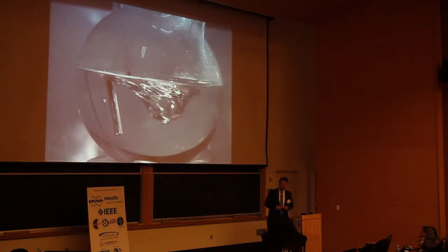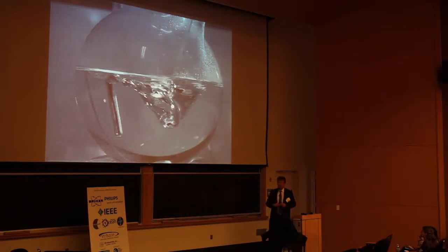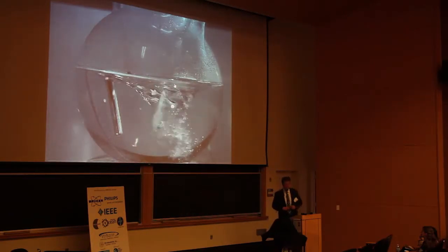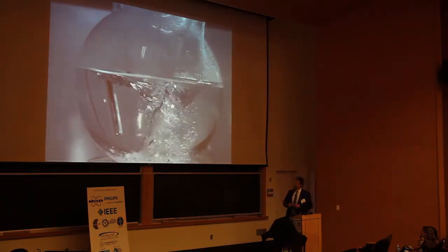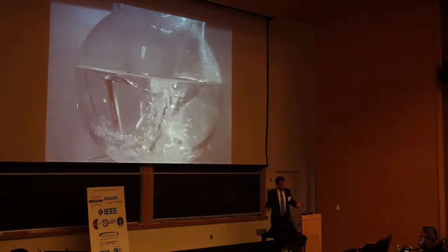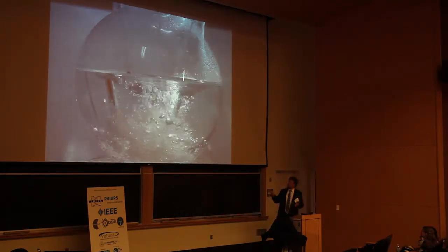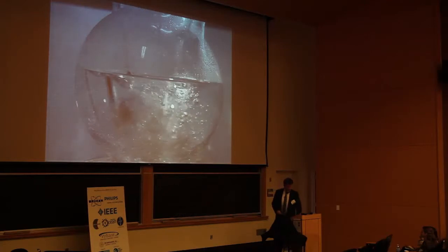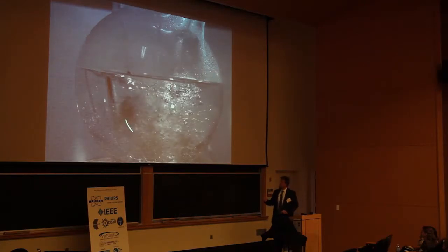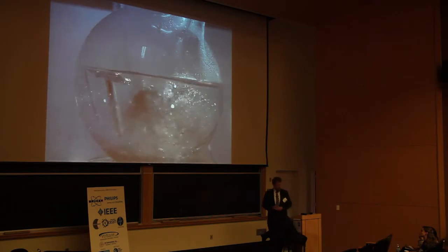This time we have a 1 liter flask, and Katerina has to inject the precursor again. But here you see she has to inject much more because it's a bigger flask, a bigger amount. And you see that the mixture during the injection is not as good as before. Here there's nearly no mixing. The injection is not really finished, so she's still injecting, but the first nuclei have already started to